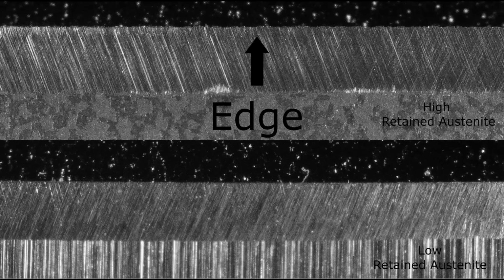So sharpenability is another complicated subject. In my prior Catra studies, which have included over 50 steels, I have only had significant issues with sharpening a small handful of the knives. This is in part due to the use of CBN abrasives, cubic boron nitride, which makes sharpening even high vanadium steels pretty easy. Instead, the difficult to sharpen knives were from the heat treating, not the steel. Those difficult to sharpen knives had high retained austenite.